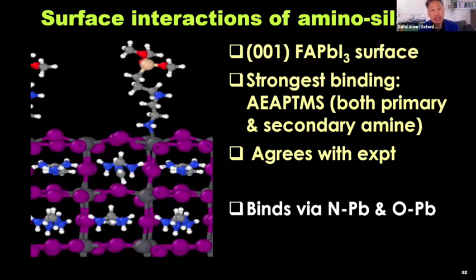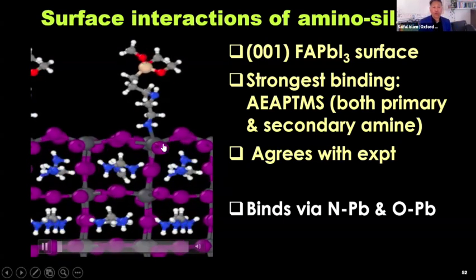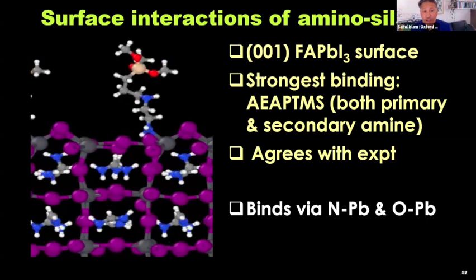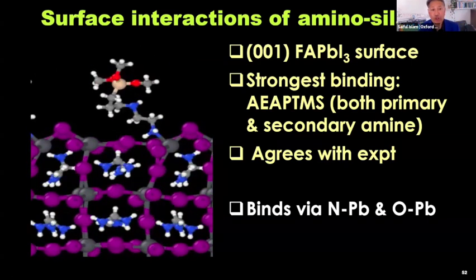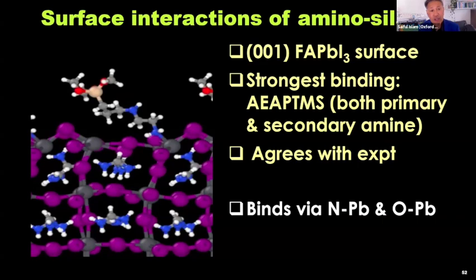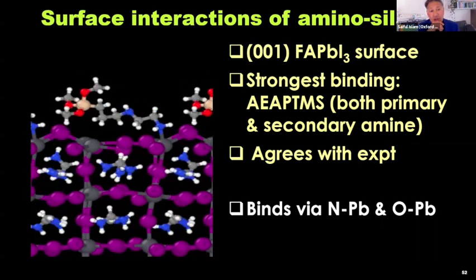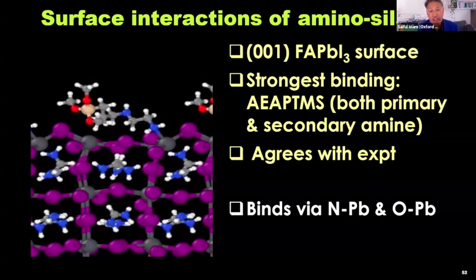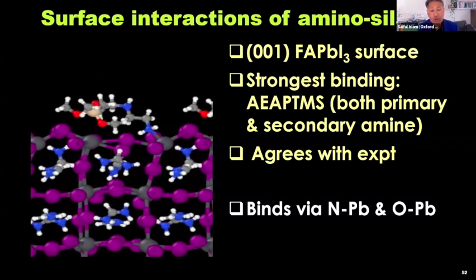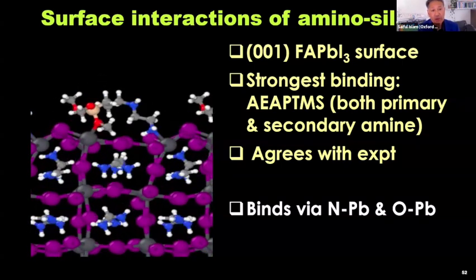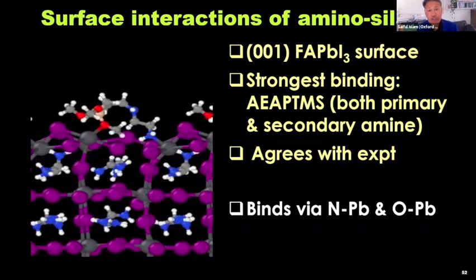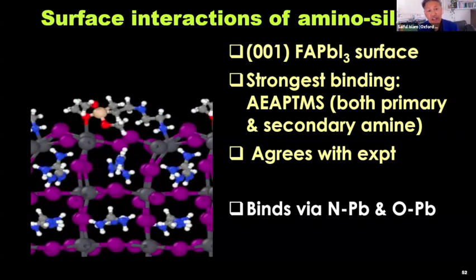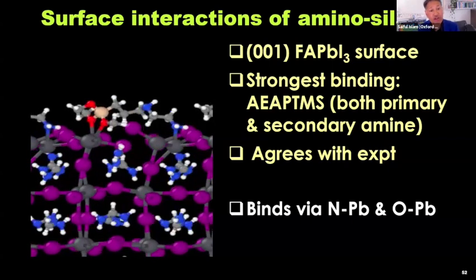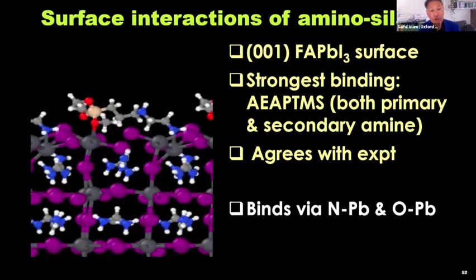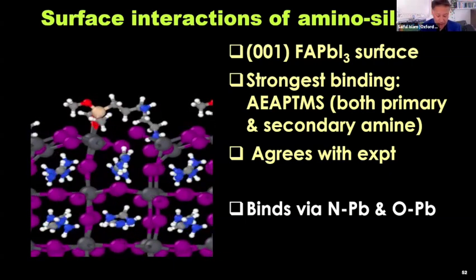But what happens during the simulation? So let me show you what happens. We see a lot of dynamics at the surface. We see that the molecule interacts with that surface. It begins to align parallel to the surface, but binds strongly to the lead ions, which bridges the iodide vacancy. So there's strong binding. In fact, the strongest binding was for this molecule, which agrees very well with experiment, because we're showing that it's actually the highest binder.